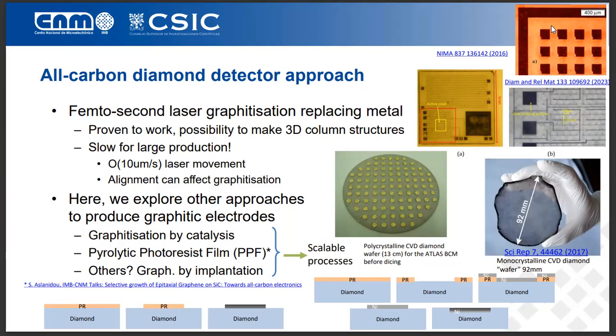Here I'm naming some. Graphitization by catalysis: you deposit nickel, and nickel acts as a catalytic material, and after annealing, you get graphite on top of the diamond, on the surface of the diamond. Then pyrolytic photoresist film: you do pyrolysis on the photoresist resin. This has been shown in a previous CNM talk by Sophia, and that was done on silicon carbide.